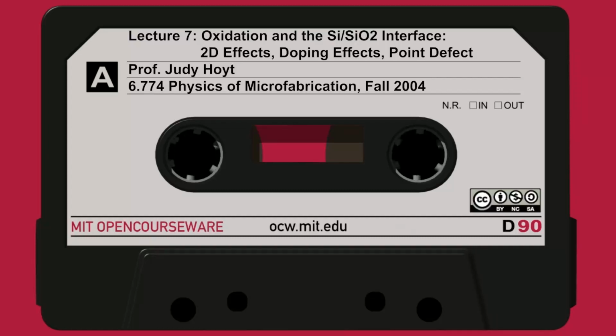Remember, some interstitials get injected into the bulk, some go out. There's a few that get stuck near the interface, this little extra silicon interstitial with a positive charge on it. It's not bonded to oxygen atoms, so it has an excess positive charge. Those unbonded, extra dangling silicon interstitials that are positively charged are believed to be responsible for QF.